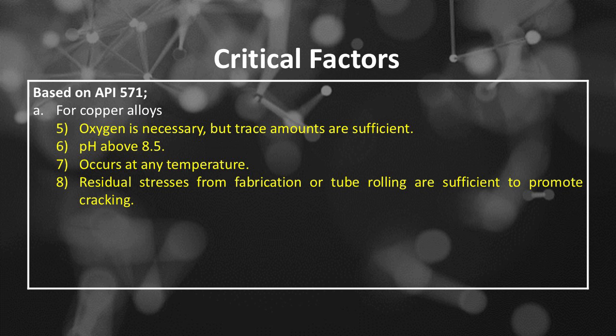Number 5, oxygen is necessary, but trace amounts are sufficient. Number 6, pH above 8.5. Number 7, occurs at any temperature. Number 8, residual stresses from fabrication or tube rolling are sufficient to promote cracking.